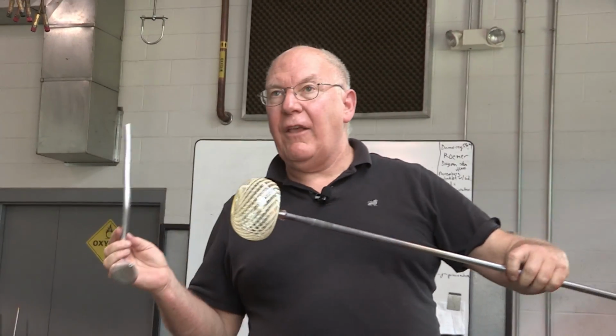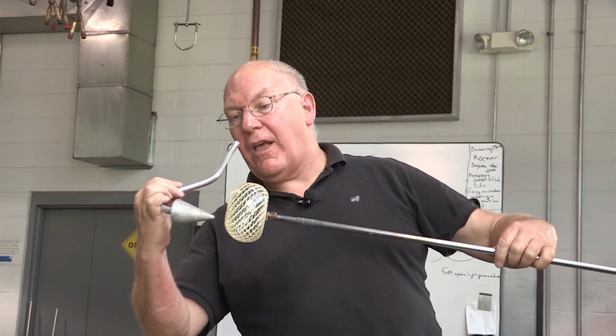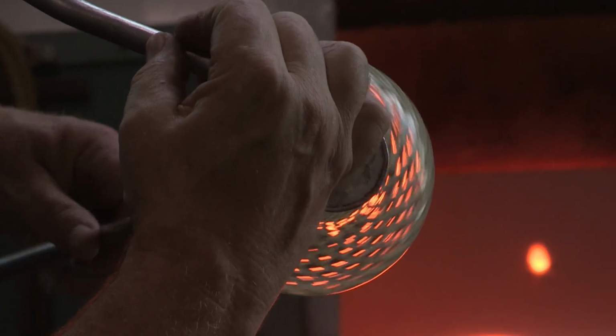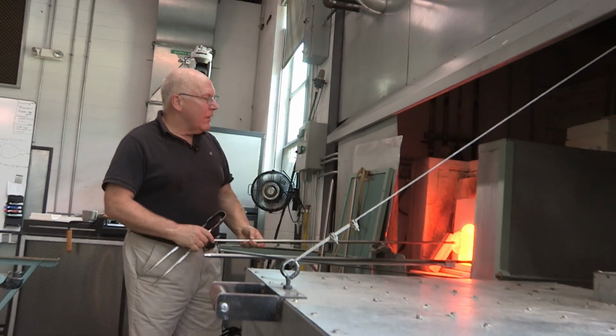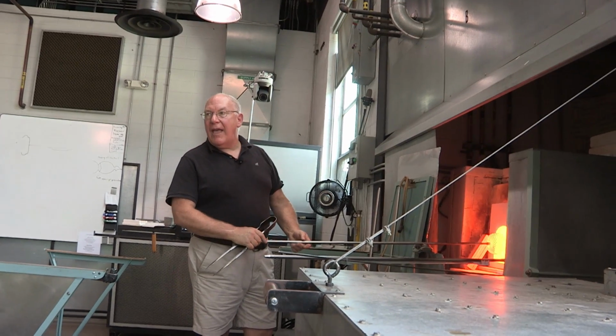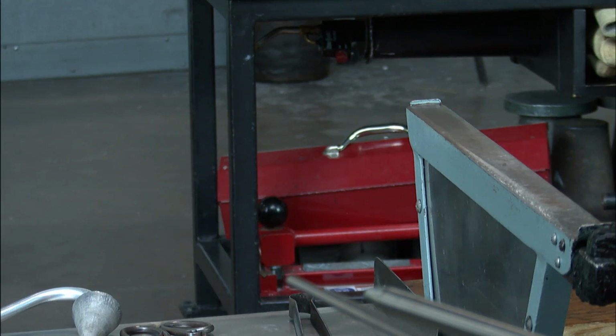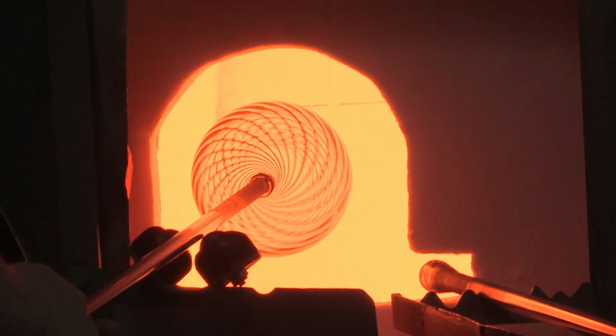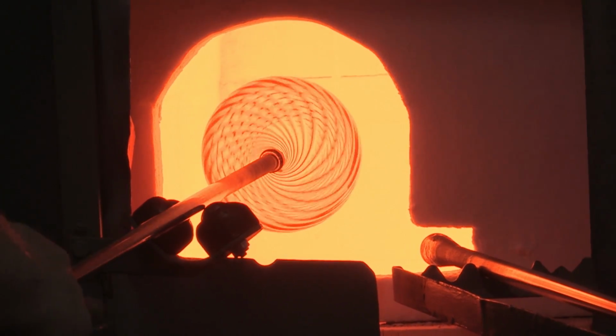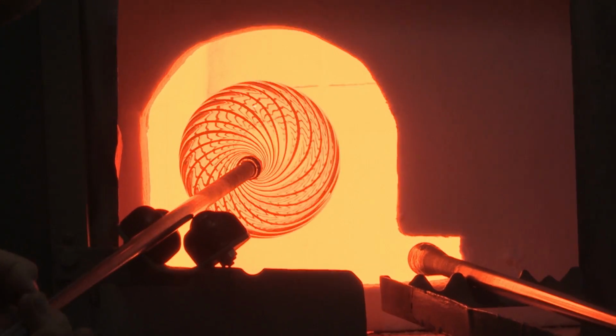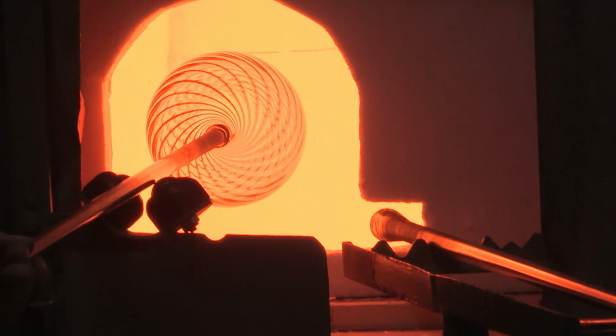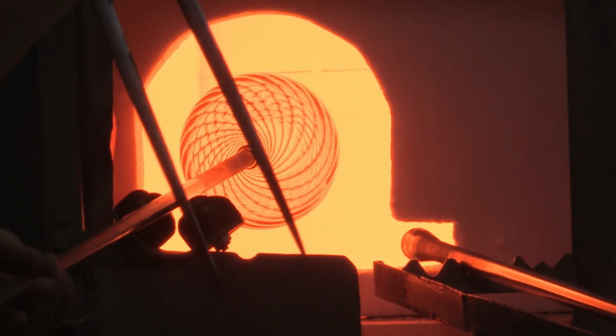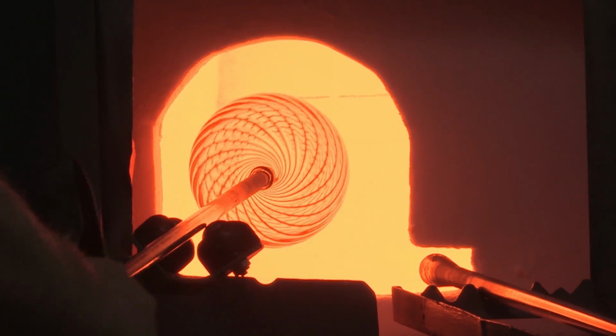I'm going to let the thin glass cool. Now the only thing soft is the thick glass. I'll blow a second at a time, and it blows the lip area a little thinner. And here comes the external or outer fold. This is quite a bit more trouble, more difficult than an inner fold. An inner fold is relatively easy. You push the edge in and lift. You just saw that. The outer fold requires a little more manipulation.